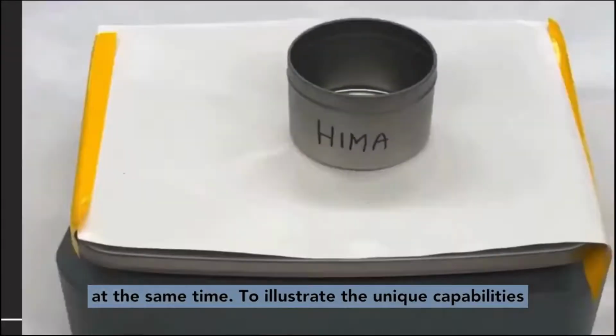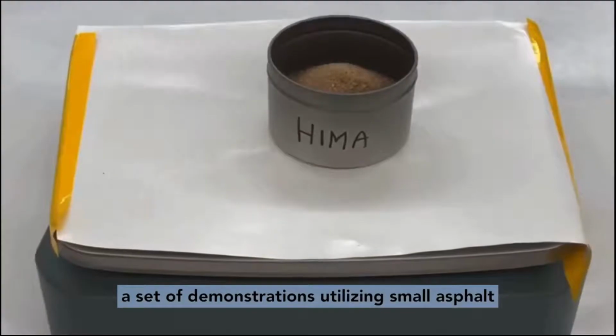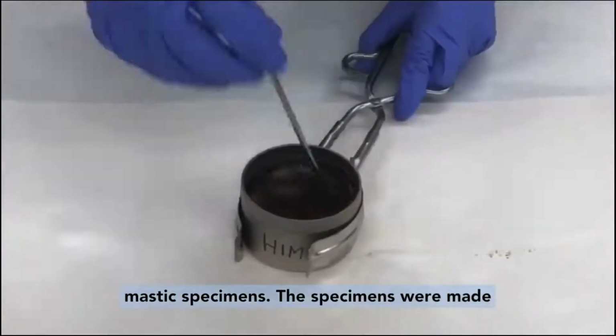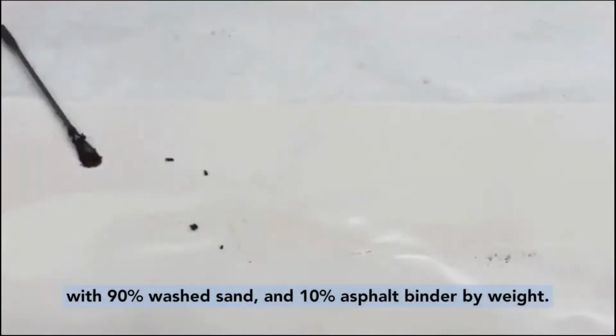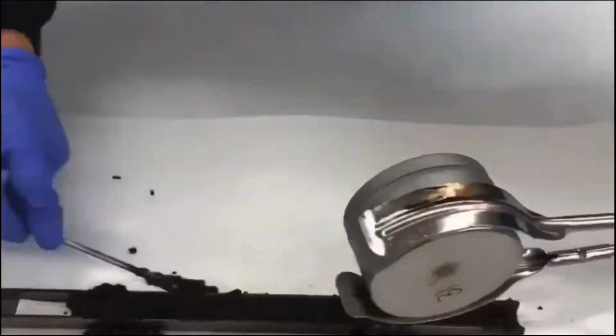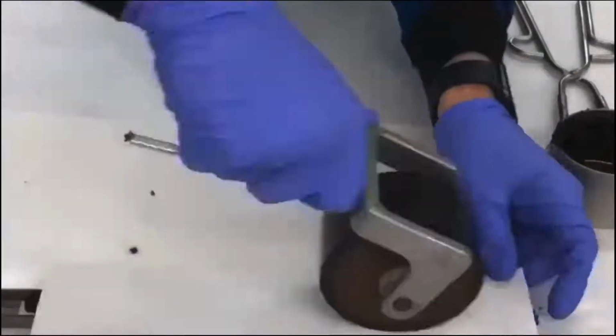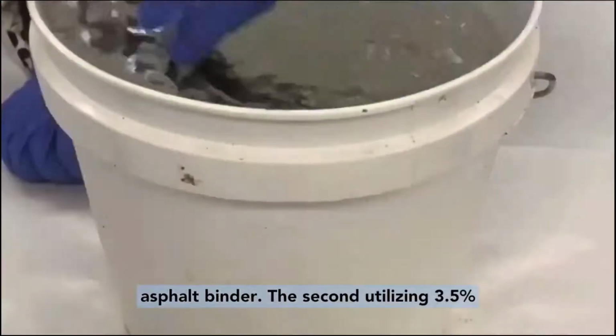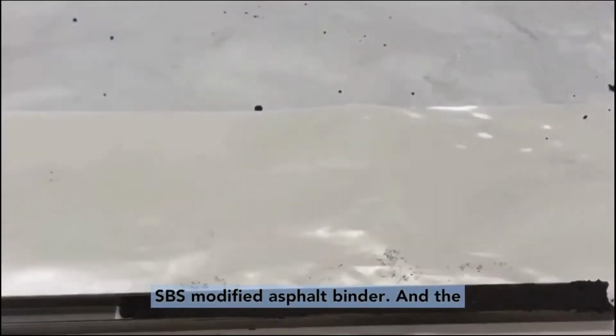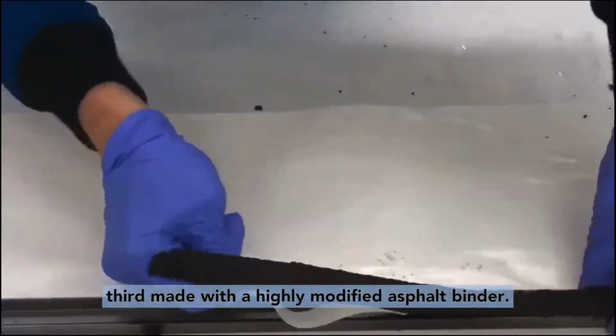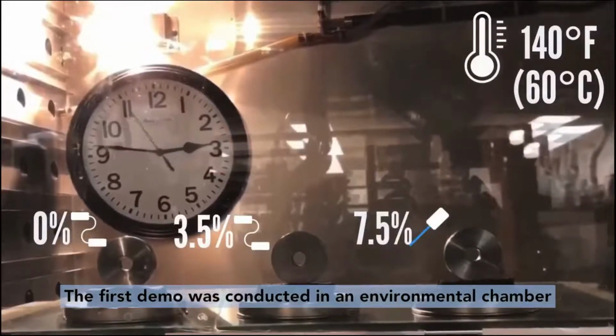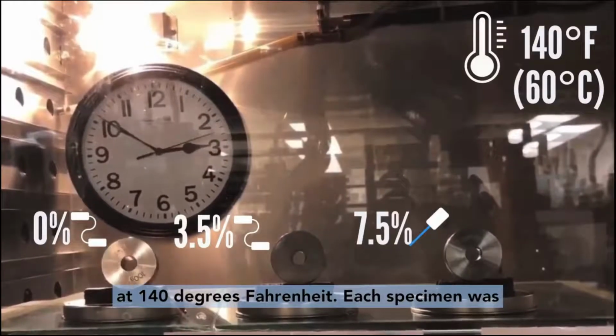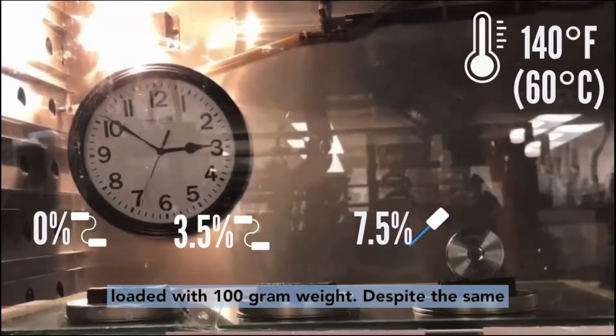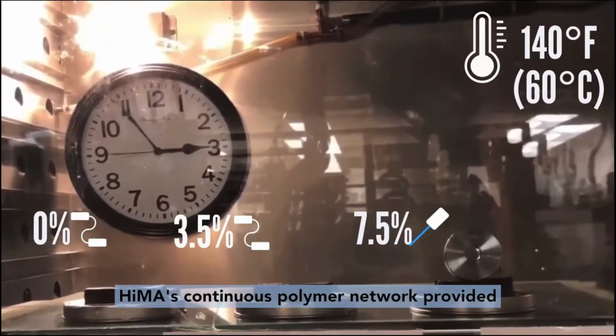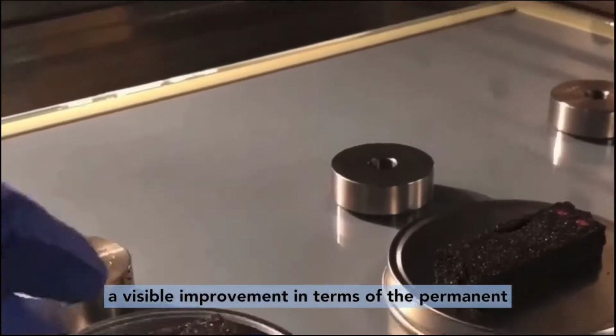To illustrate the unique capabilities of the HiMA technology, we have prepared a set of demonstrations utilizing small asphalt mastic specimens. The specimens were made with 90% washed sand and 10% asphalt binder by weight. Each demonstration features 3 specimens. The first made with a conventional paving asphalt binder, the second utilizing 3.5% SBS modified asphalt binder, and the third made with a highly modified asphalt binder. The first demo was conducted in an environmental chamber at 140 degrees Fahrenheit. Each specimen was loaded with 100-gram weight. Despite the same aggregate and binder content in mastic, the HiMA's continuous polymer network provided a visible improvement in terms of the permanent deformation resistance.